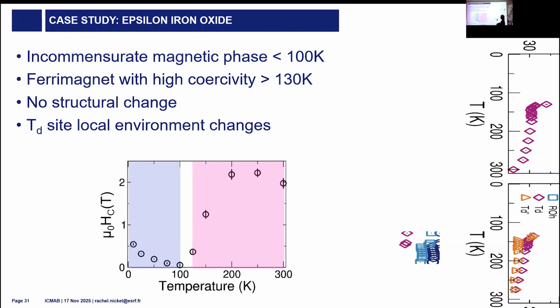So in the Mossbauer, we see that there's a significant change in the tetrahedral local site. There's a significant drop in the hyperfine field of the tetrahedral site. And this tells us that there is a change in electronic structure. I can show you the data after if anybody cares.